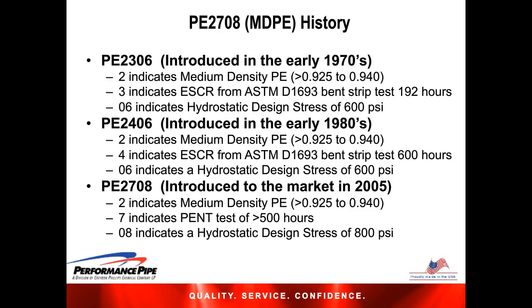These next two slides show the long, successful history of medium-density pipe in the United States. When the first medium-density pipe was introduced in the early 1970s as a PE 2306 material, it had a 600 psi hydrostatic design stress. In the early 80s, PE 2406 material was introduced with increased slow crack growth performance. In 2005, PE 2708 material was introduced with an even greater slow crack growth requirement based on PENT testing. The material also achieved an increased hydrostatic design stress of 800 psi by meeting the criteria for a high-performance PE material.